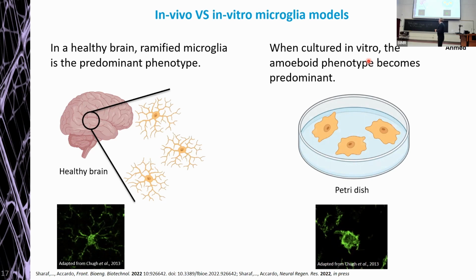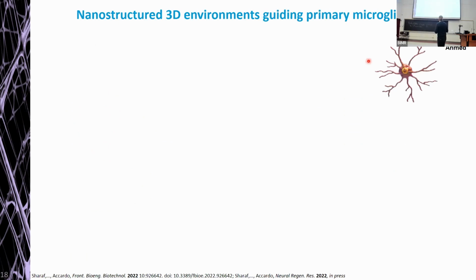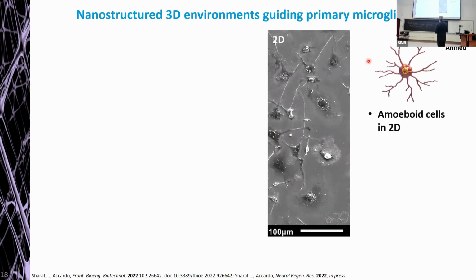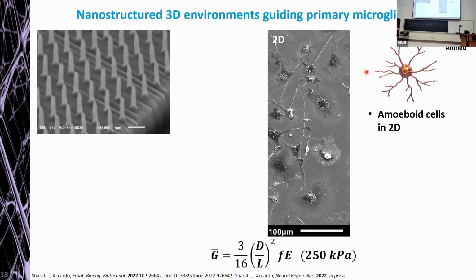Okay, we look at this microglia, and then we had a look at them at the SEM on 70 gigapascal stiff glass. And as we were expecting, we observed a few ramified microglia, but mostly amoeboid ones, shrunk ones. And then by 2-photon polymerization, we started to create extremely fine, extremely accurate nanopillar carpets, where in particular we exploited the concept of effective shear modulus.